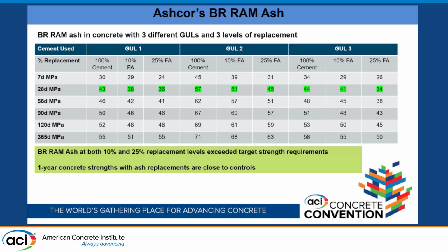So we took that Battle River RAM ash and we made a few different concrete mixes with 3 different GUL cements that are famous in this region of Ontario: GUL1, GUL2, GUL3. We replaced all the GULs at 10% and 25%. Our target was 30 MPa at 28 days, and the water was fixed on all these mixes. As you can see, all the concrete mixes met the requirement of 30 MPa. And it did not stop there. The reason I put this chart up here is that the concrete continues to gain strength without compromising any strength. So by 1 year, they're almost close to the control.